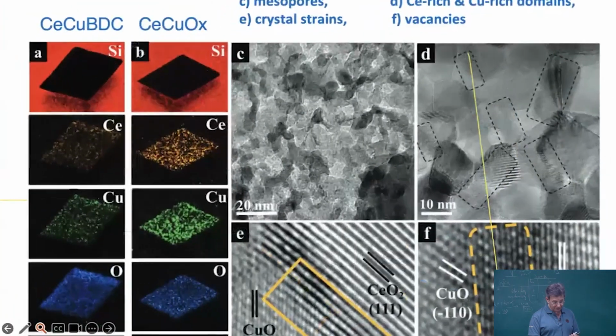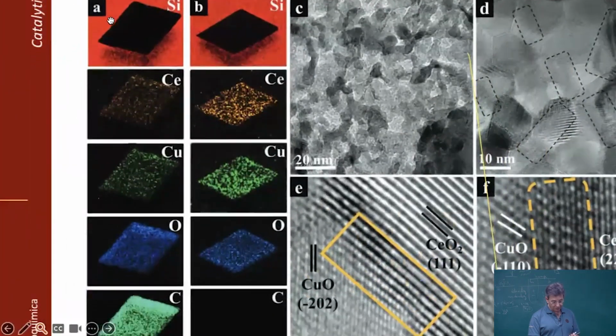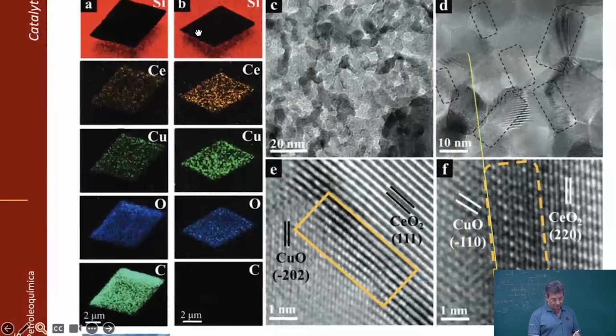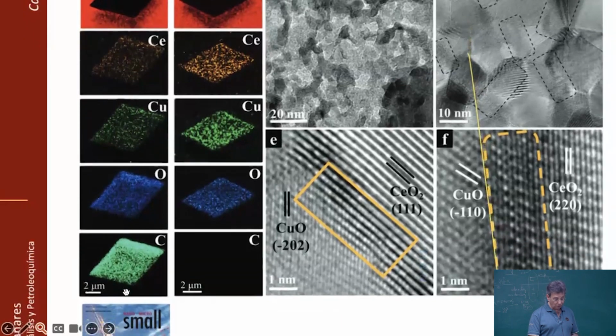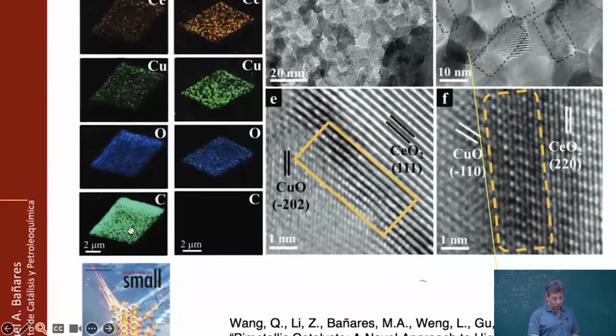So here you have the element composition from the electron microscopy. You see that basically there is no silicon there, but we do have ceria before and after the combustion of the MOF. You also have copper, and the distribution appears to be pretty random, so that should be a good interaction between the copper and the ceria. Of course, oxygen is still there after the combustion, but all the carbon and all the organic part of the MOF was burnt away, because it is an organic ligand, so you burn it away, and there is no longer any organic part.